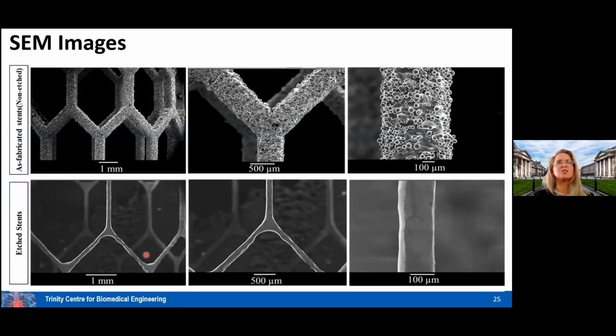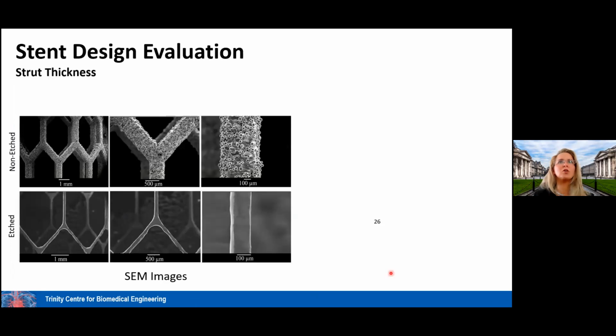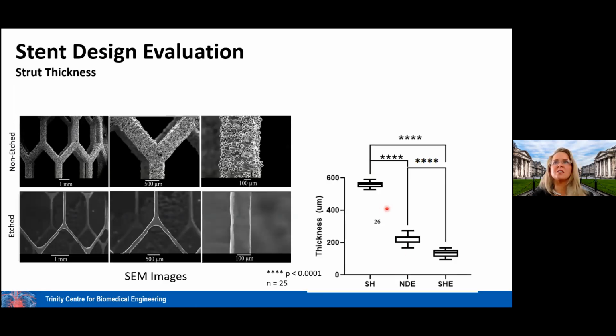And here we can see some closer-up scanning electron microscopy images of our as-print stent with all those defects and all of that dross and particle attachment. And here you can see the nice surface finish that we can get once we etch. But let's look at this in a bit more detail. We can see that the thicknesses definitely have reduced and we have thinner struts for this simple honeycomb etched, as I said, around 150 microns, whereas around 200 microns for the novel design etched one. And that's compared to what it was in as-print, which was just over 500 microns.